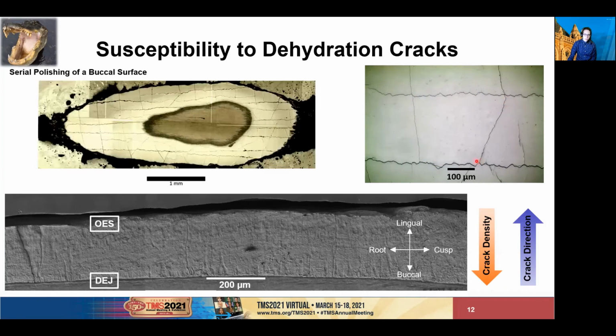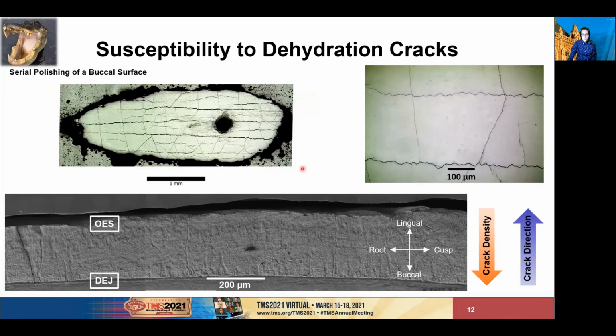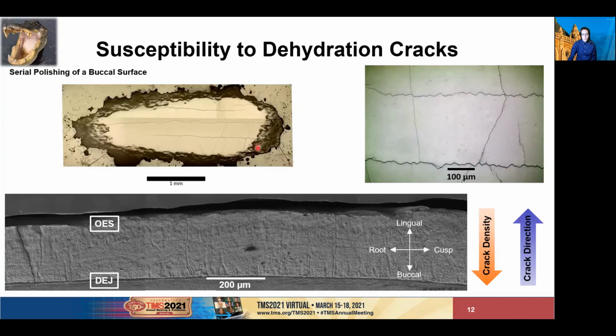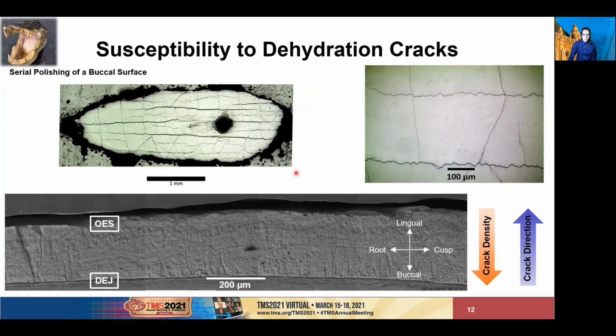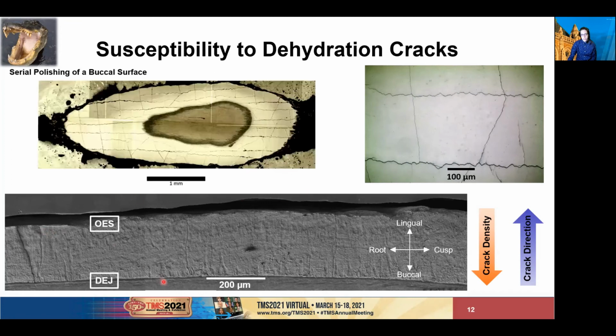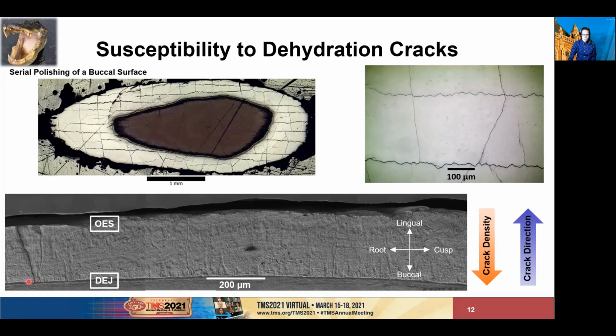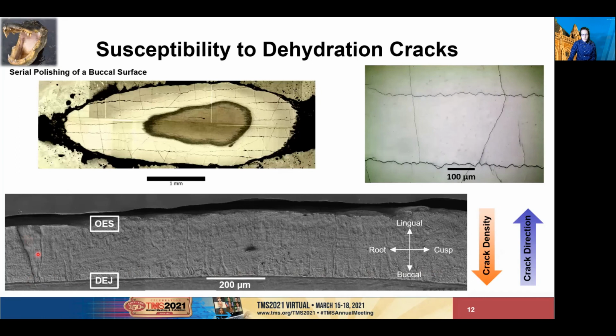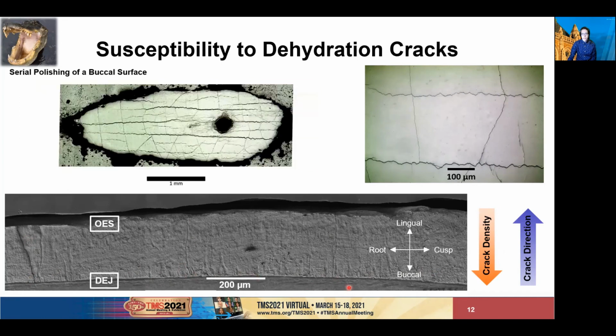If you watch closely, you can notice that the positions of the cracks do not really change as you move through the enamel. You can also see the extent of the cracks in this buccolingual section micrograph here on the bottom, where in just about a millimeter, we see 3 large cracks stretching through the entirety of the enamel.